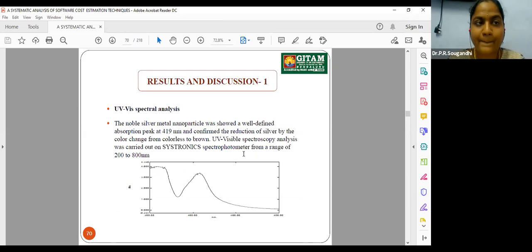So coming to the result and discussion in brief, we can see the UV visible spectral analysis, which is the silver nanoparticle characterization. Here we can see an absorption peak observed at 419 nanometers, which confirms the presence of silver nanoparticles. And here we can also see the color test. The color changes from colorless to brown, which indicates the reduction of silver nitrate to silver nanoparticles.